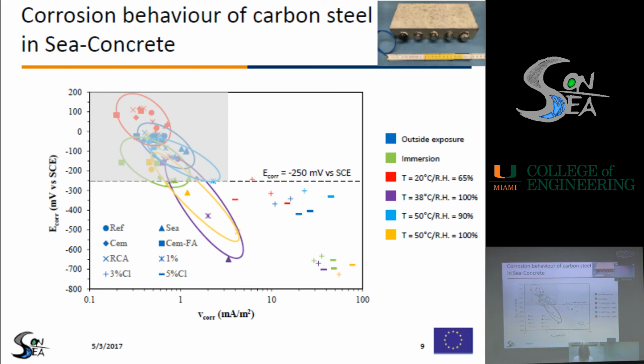We can observe in this figure that in the most aggressive conditions, those with high temperature, so around 40-50 degrees, and high relative humidity, around 100%, the values were below the threshold, indicating that in this condition the carbon steel bars were corroding, and so were active. Carbon steel bar was also active in less aggressive conditions, but when it was embedded in the concrete with the highest chloride content, so in the concrete with 3 and 5% of chloride. So this test showed that, as expected, carbon steel bar was unsuitable when embedded in concrete with a high chloride content and in the harsher environment.